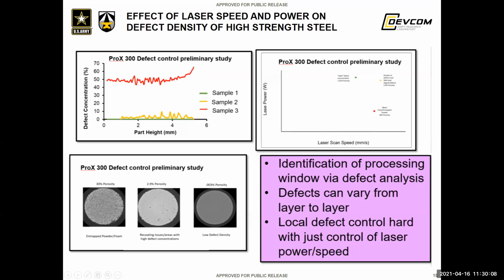So for this one, we had laser processing parameters where, if we had to, we probably could create a small powder foam. However, if it's a larger part, it'll probably just break apart in the manufacturing process. And then we're able to establish that there are some recoating issues with this one, or high areas of defects, but maybe we could control it. It's kind of erratic, it goes high and low, so there are obviously some coding issues. This one just seems all over the place, while the final part has a low porosity that's continuous throughout. So we were building this defect study in order to fill in this laser power and scan speed map. If we made mechanical test specimens, we'd be able to know where to choose from.